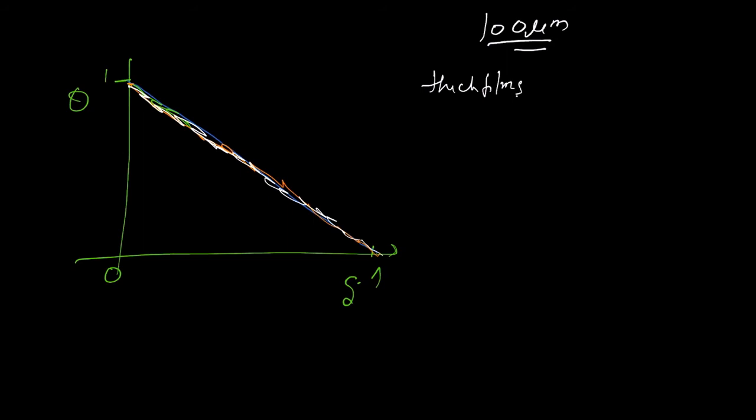At short time scales, of course, there would be some difference. We are plotting a steady state. At short time scales there would be thermal front development, and it would slowly propagate. But in the steady state, all three solutions would overlap. If we go back to the case of thin films, the solution of the Boltzmann transport equation won't overlap with the isothermal boundary condition.